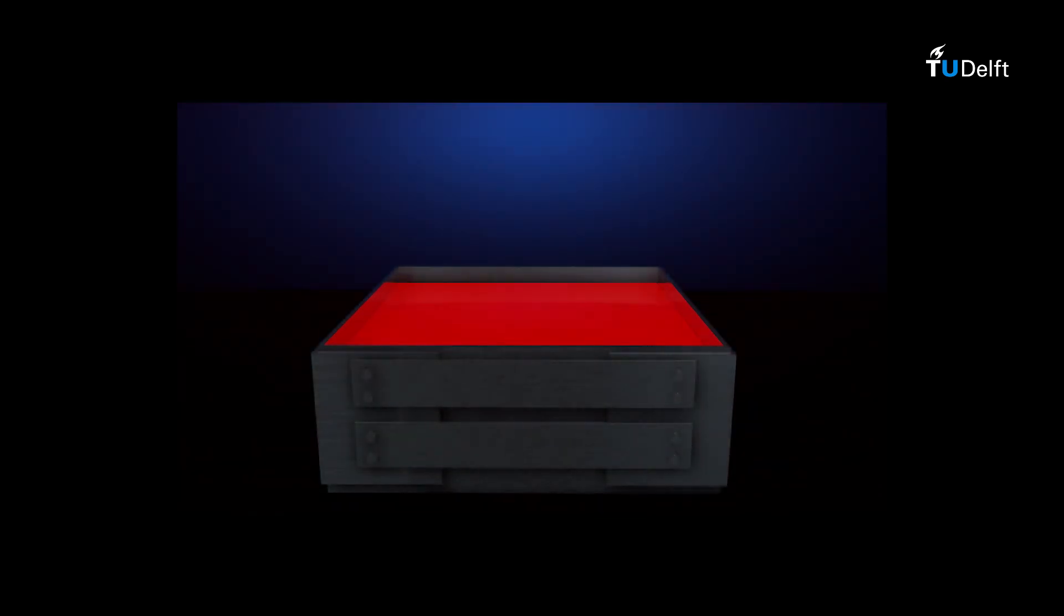If the melting and the solidification occurs in the same crucible, it is referred to as directional solidification. The cross-section of a multicrystalline ingot can go up to 70 by 70 cm and the height is typically 25 cm.